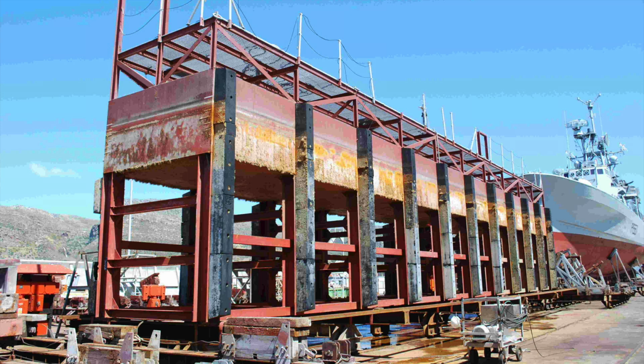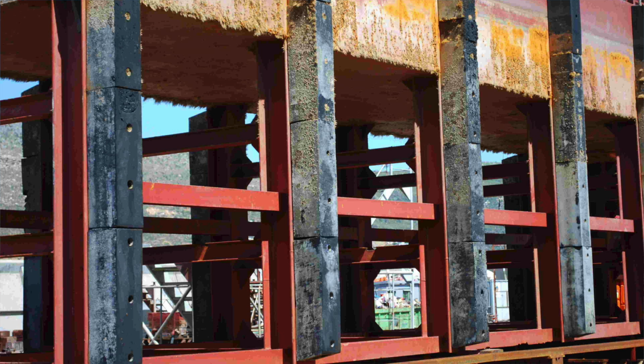But here's an example now where this floating pontoon was alongside, but it's very important that it is earthed. Otherwise, you start to get galvanic corrosion between the floating pontoon itself and the quayside. And this is actually what had happened. You can see there's a very even distribution of brown. There you go, all the way down that side. And that's a classic example of stray current corrosion.